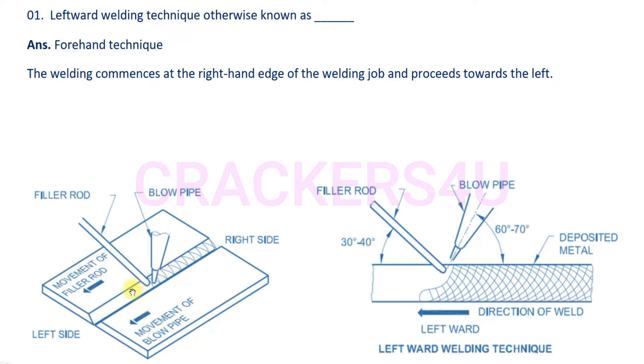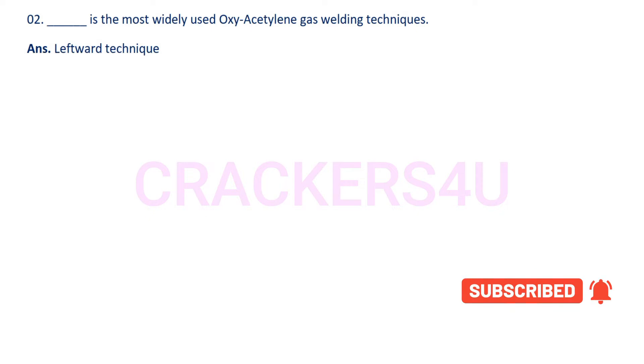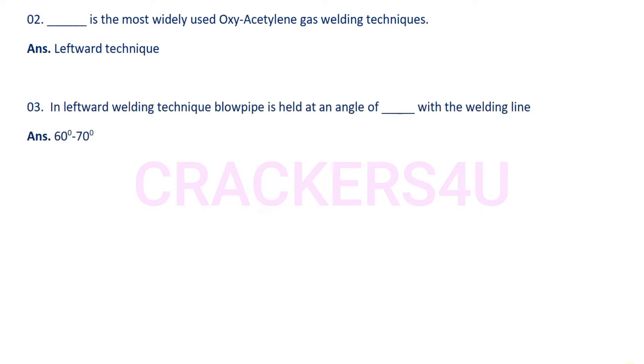Question number two: The leftward technique is the most widely used oxy-acetylene gas welding technique. In the leftward welding technique, the blow pipe is held at an angle of 60 to 70 degrees with the welding line.